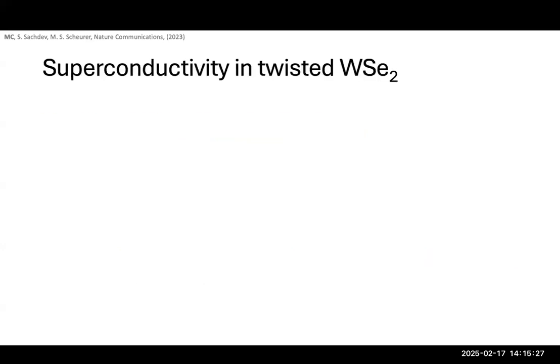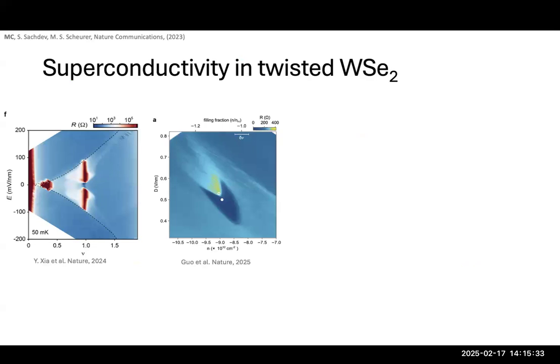So I want to talk now about superconductivity in twisted tungsten diselenide. So earlier this year, in the summer, superconductivity was observed in twisted WSe2 in Kin-Fai Mak's group and Cory Dean's group at Columbia. So this is the data from the Cornell group, and what they see is superconductivity at integer filling equals 1. And then as they turn on the displacement field on the y-axis, you undergo a phase transition to some type of insulating state.